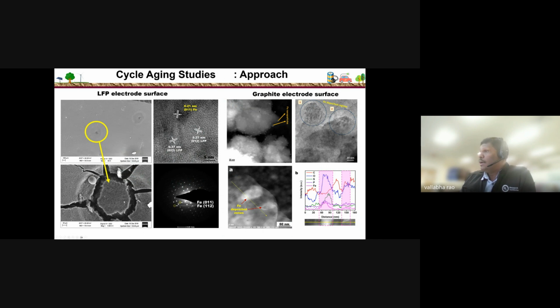We can clearly see that the iron particles dissolved from the cathode and then deposited on the surface of the anode. Where these cathode transition metal particles were deposited on the anode surface, the SEI layer formation or electrolyte decomposition also occurs, which causes continuous film growth in those areas. This clearly indicates that when transition metal dissolution occurs, the deposited metal acts as a catalyst to decompose the electrolyte continuously and form the SEI layer on the surface. When this SEI layer forms, it consumes the active lithium ions. As a result, the capacity fade is accelerated.